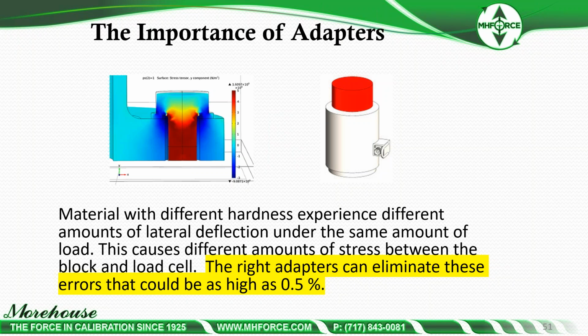And the reason it can be problematic is that materials with different hardness experience different amounts of lateral deflection under the same amount of load. This causes different amounts of stress between the block and the load cell. The right adapters can eliminate these errors that could be as high as 0.5%. I've done numerous tests with this. Hard blocks, the hardness of the material, make a huge impact on load cells.